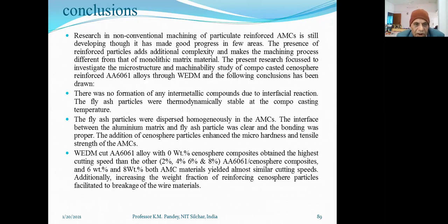Conclusion number one: there was no formation of any intermetallic compound due to interfacial reaction. The fly ash particles were thermodynamically stable at the compo casting temperature. Second, the fly ash particles were dispersed homogeneously in the AMC. The interface between the aluminum matrix and fly ash particle was clear and the bonding was proper. The addition of cenosphere particles enhanced the microhardness and tensile strength of the AMC.